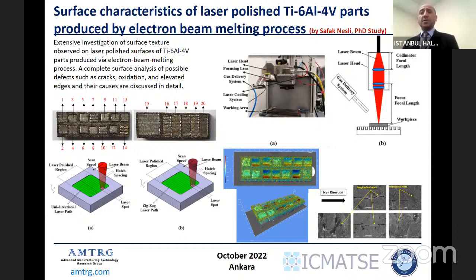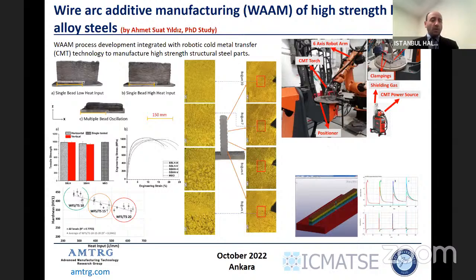One of the PhD students who already graduated worked on titanium 6-4, which was produced by the EBM process, and we got very good results. I mean, for example, EBM surfaces are about 40 Ra, and we reduced them to almost 2 Ra by using the laser polishing process. And also, some of my researchers are working on WAAM.